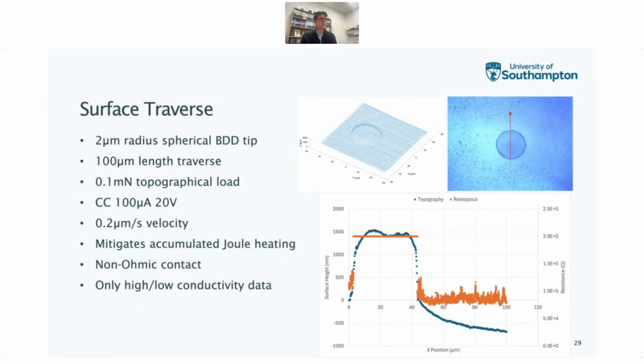So maybe we could try and do it quickly. Let's move across the surface instead of dwelling so much, but let's put a profile on there where we're tracing across the surface. So in this instance, it's only 0.2 microns per second with the 2 micron radius spherical tip, and we're going to do 100 micron traverse across this particle. So the red line here across this topography, and that shows this is a slice through there, and it does mitigate the Joule heating. So if you move along, you can prevent the accumulation of the heating. The problem is you're non-ohmic again, so you can't actually get any realistic useful resistance measurements beyond that.